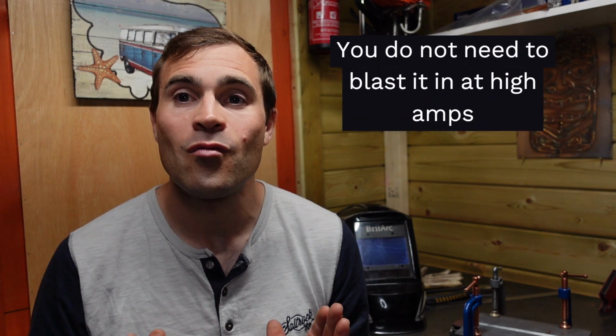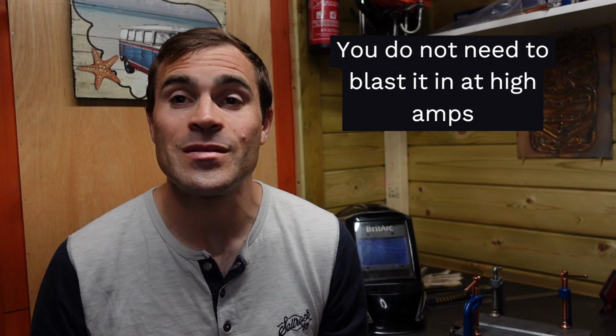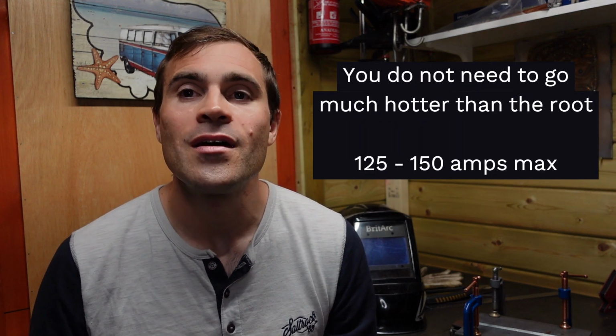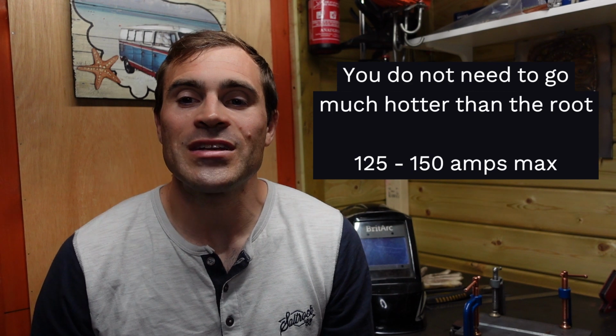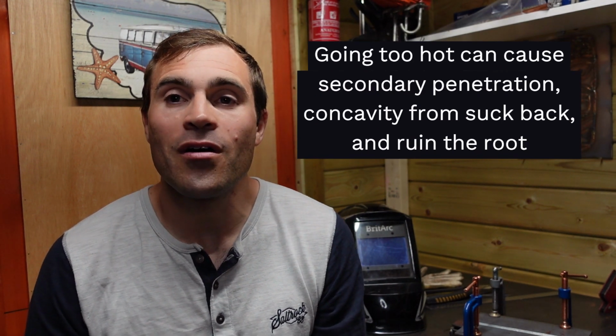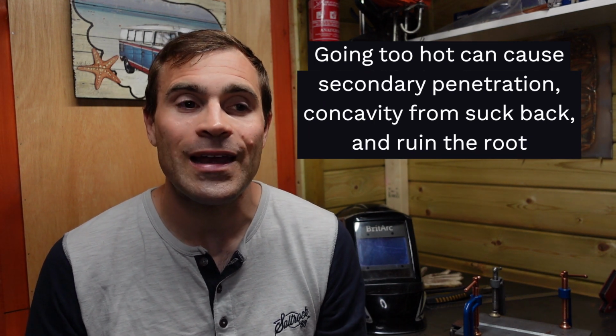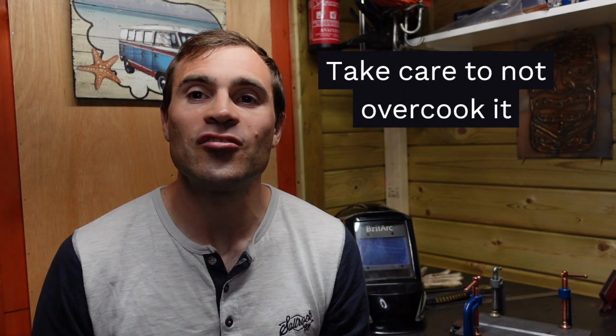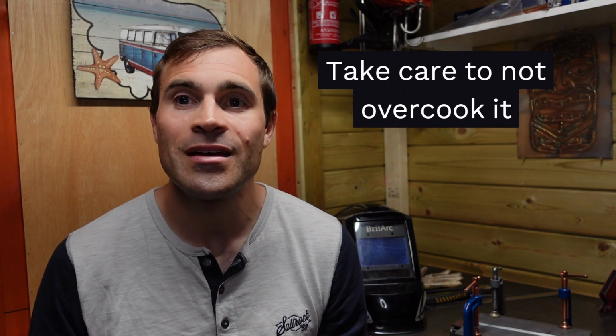Now, contrary to common belief, the hot pass is not something that needs to be blasted into the root run nice and hot. Not at all. You don't need much more amps than what you use for the root run. Remember, the whole purpose of the hot pass is to tidy up the root and put a bit of extra meat on there ready for fitting runs. You don't need to go too hot in the hot pass because you could over-penetrate the root, burn through, create suck back, create lack of fusion, create a variety of defects which will be picked up in x-ray. So go gentle with the hot pass, you need to do it, but don't go crazy.